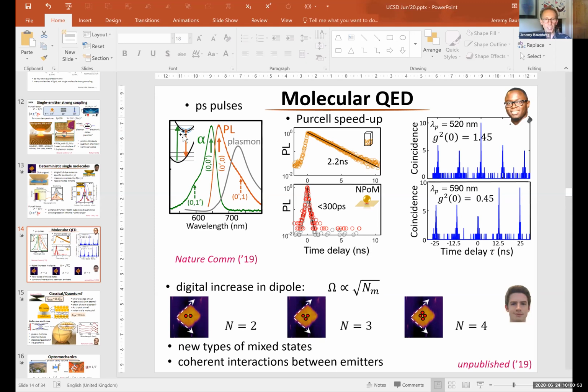So we now have various theory groups trying to understand. The system was already published last year. There really isn't a full theory for this system, because what you have to do is you have to also include the relaxation in the molecular system. So you need to dress all the vibrations in the system, and not just a single mode, because you have also vibrational relaxation here as well. So it's easier somehow in a semiconductor system where we don't normally think about shifts. We think about essentially in a semiconductor system, it emits at the same energy because the phonon relaxation is slower. That's absolutely not true in the molecular system.